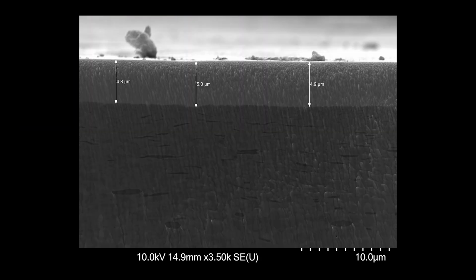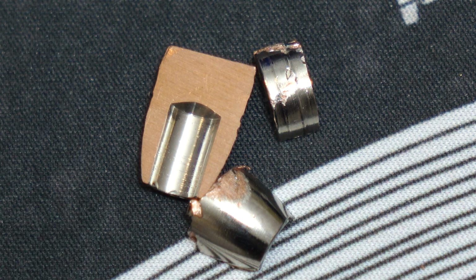The coating is what we're really here to see, though, and the EDS tells me it's nickel. And from the images here, I measured it to average about 4.9 microns thick. So the nickel coating is going to provide some corrosion resistance to the bullet, so that's good. But a copper core bullet with a nickel coating is also going to be more expensive than the usual lead core and copper jacketed bullet. So as for how this is made, my completely uneducated and most likely wrong guess is this. These copper bullets are machined to the correct shape and weight, and then the bullet is given a nickel coating, possibly through electroplating. But as I said, I have no idea.